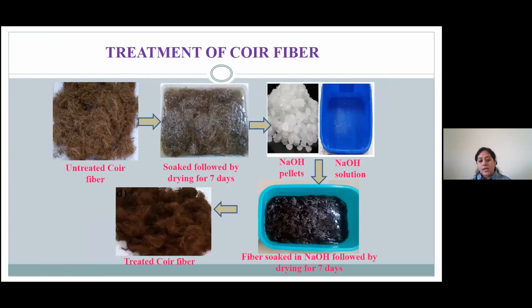Since the natural fibers always have the problem of biodegradability, the cellulose and hemicellulose rich natural fibers were chemically treated with 10 molar sodium hydroxide solution prior to use.